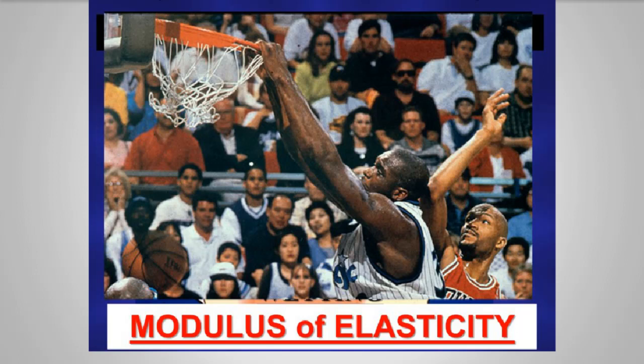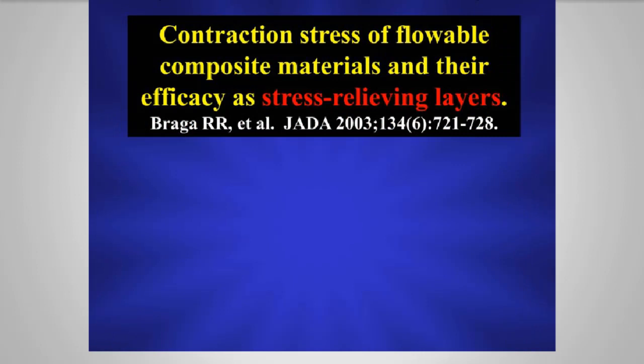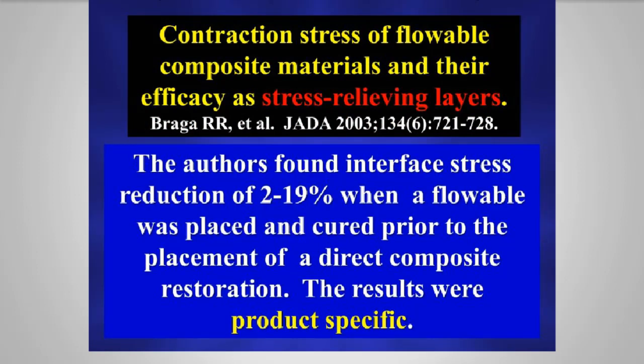Although that is controversial, there are some studies that show that it may have some merit. I'm citing one right here. In this particular study, the author found an interface stress reduction of 2%, which is not clinically significant, to 19%, which probably is clinically significant, when a flowable was placed and cured prior to the placement of a more heavily filled composite material. What they found was that the results were product specific. My guess would be the lower modulus flowables performed better in this study than the higher modulus flowables did.